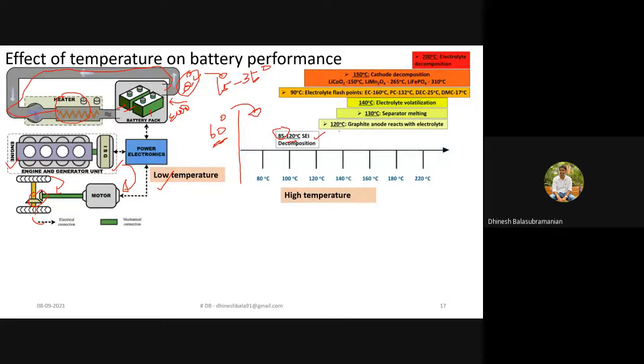And after 120 degrees, the graphite anode would react with the electrolyte. The graphite anode is like a swimming pool area. Initially, this graphite won't take part in the chemical reaction. But once graphite starts to react with the electrolyte, which is nothing but the barrier, the thickness of the barrier would get reduced, and that would create an additional option for the flow of electrons in the horizontal direction. And at 130 degrees Celsius, the separator would start to melt. At 140, electrolyte volatilization would happen. And at 150, the cathode decomposition would happen.